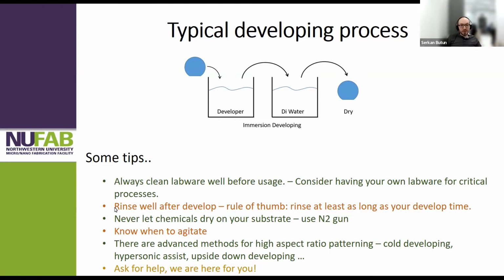Now, the second thing is often omitted a lot, especially with beginning users, that you have to rinse very well after the develop finishes, because the idea of rinsing is first, it will stop the development process, and also it will clean the substrate surface from dissolved developer, right? Otherwise, you'll have a lot of scum at the bottom of your features, especially around the corners, and you'll get surface roughness. Maybe if you're doing a lift-off process, you get delamination.